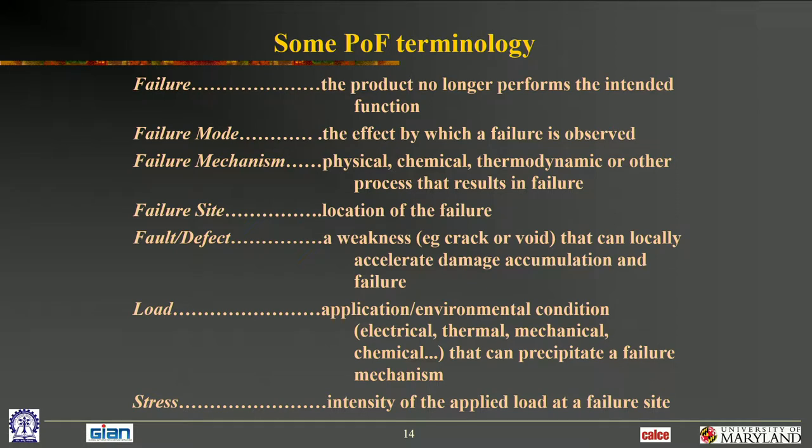Because if you want to go back to your capacitor supplier and say, I need a better capacitor, it's not enough to root cause it down to the capacitor. You need to know what within the capacitor is causing the problem. So the capacitor manufacturer will probably take apart the failed capacitor and try to find out what's going on. They may find that they've got excessive cracking inside it, the dielectrics are cracking, or you've got metal migration, dendrites that have formed within it. So they are going to root cause it down to, is it the dielectric that's the problem, or is it excessive metal migration? So you're root causing it down to a material, okay?